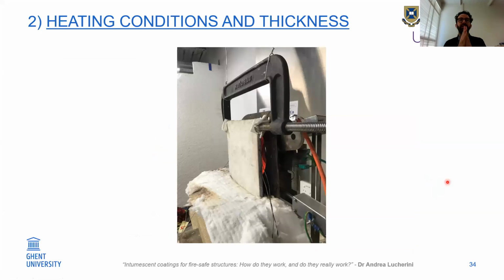Particularly what is interesting is that then we start thinking, okay, what happens if we sort of flip the reaction of the intumescent coating? So you can see here, for example, the same steel plate, and here you can see a bit of the cone calorimeter. So what I mainly did, I applied a heat flux, instead of from the surface of the coating towards the steel, from the back of my plate towards the intumescent coating. So I mainly flipped the thermal gradient inside the intumescent coatings.